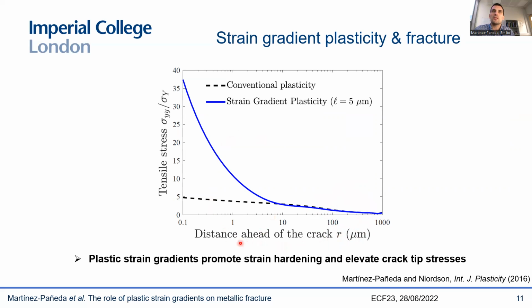However, very often we have situations, and this is relevant to the experiment that we were discussing before, where you had a critical distance very close to the crack tip, within the order of 1 or a few microns. And there you can see that the stresses can be very different depending on which assumption you take. So if you're neglecting the role of GNDs and plastic strain gradients, you're really significantly underestimating your stresses.